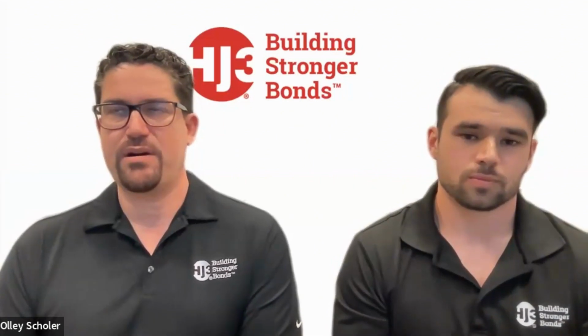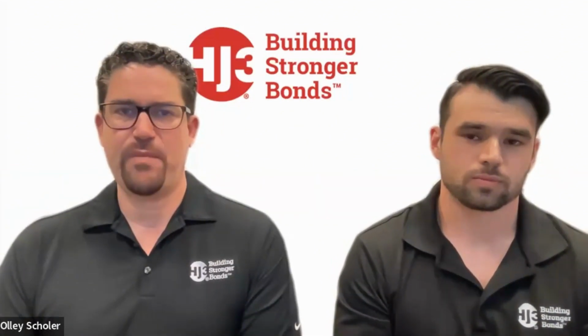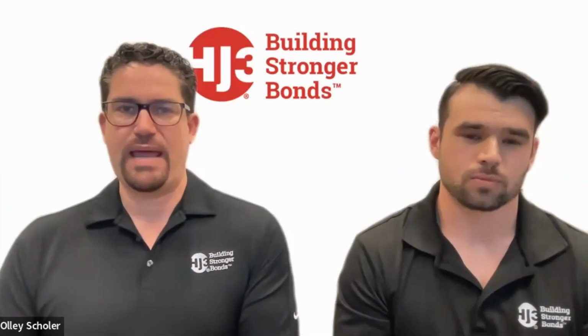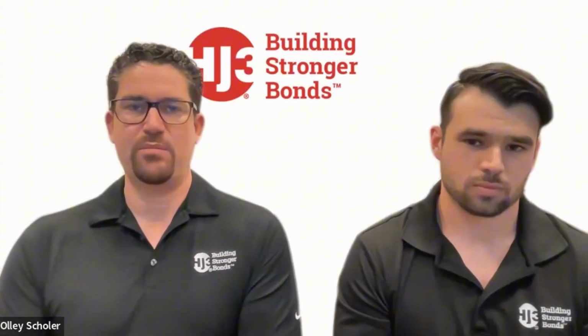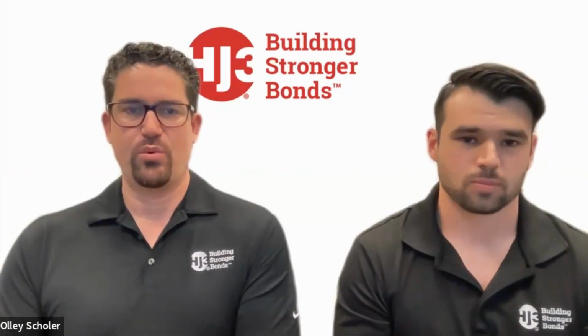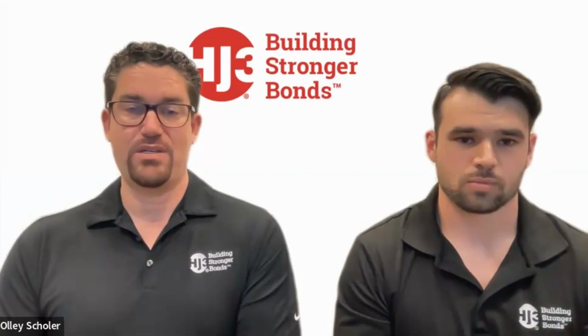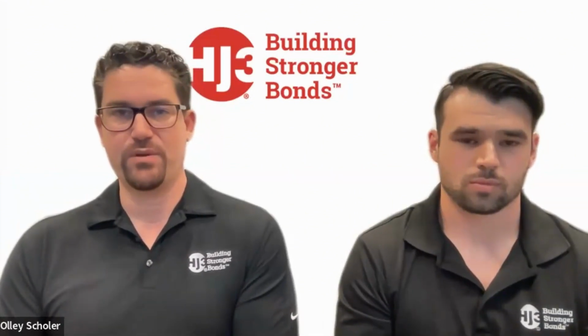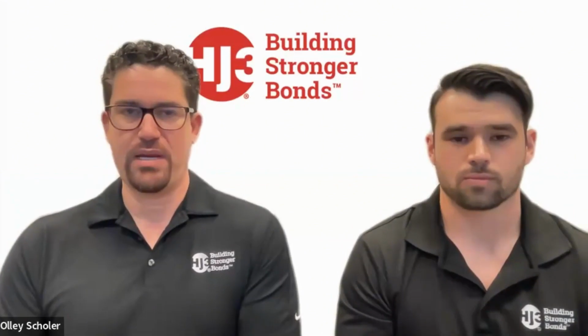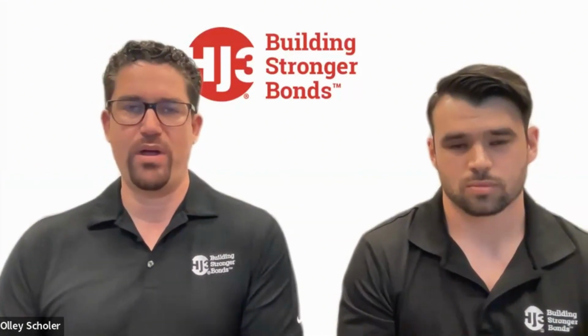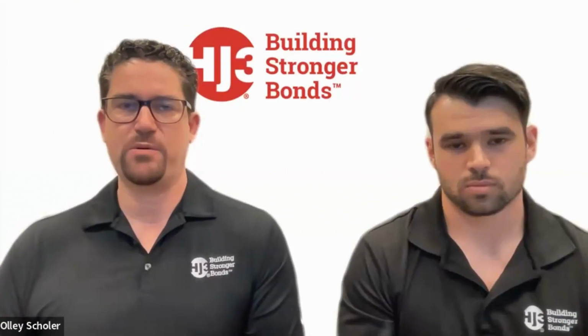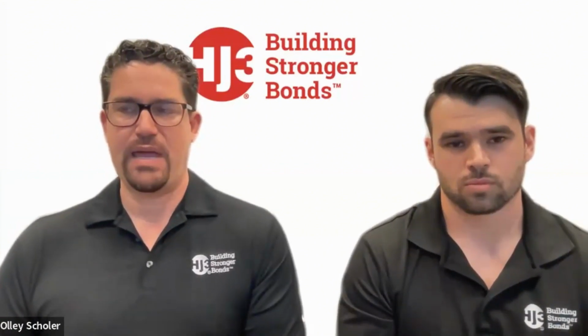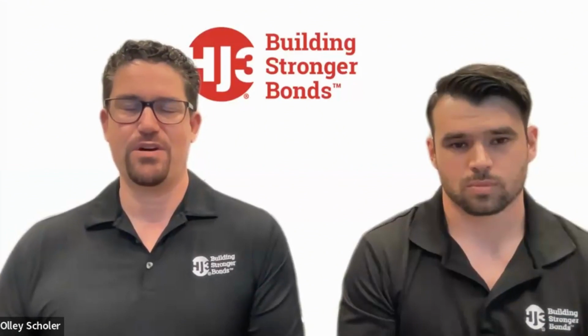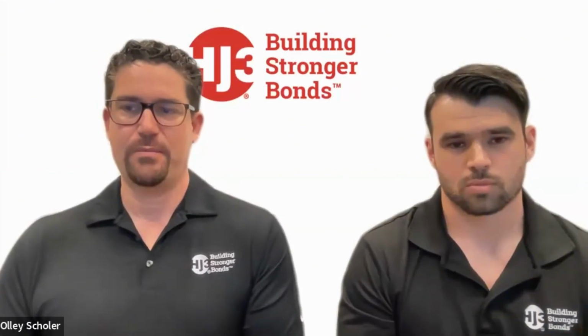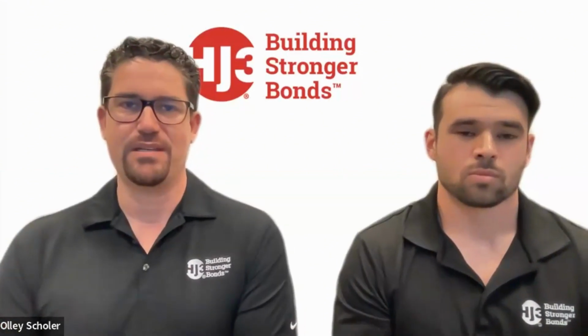And I would say our greatest feedback, our most positive feedback from clients is that we can provide an external repair system without damaging the internal liner. So with a welded repair, that's going to create a lot of issues. It could destroy the internal liner, leading to further corrosion. And it can also create a heat affected zone around that weld. And that heat affected zone will capture a lot of residual stress. And eventually that will want to come out over time. So if you're in a very active state of corrosion, that residual weld stress will start forming different cracks and other defects that aren't good.